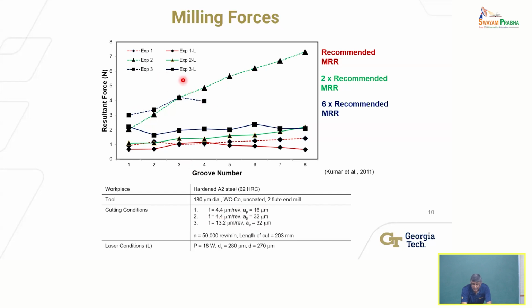Now let's look at the corresponding case where we had the laser. Okay, so this is 3-L, which is this one here. And you can see it continues more or less with very little change in the force over 8 grooves. And we stopped there. We could go further if you wanted to. Now, for the extreme case, it says that with laser assist, I can machine at 6 times the material removal rate. If I didn't use the laser, the tool will fail. I can increase the feed and the depth of cut, so the volume of material removed can be increased much faster. That's the advantage, okay? One advantage anyway.